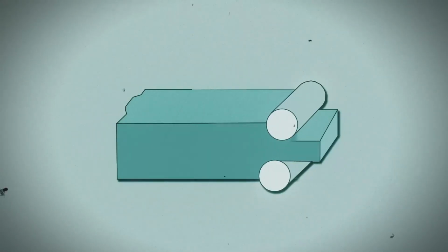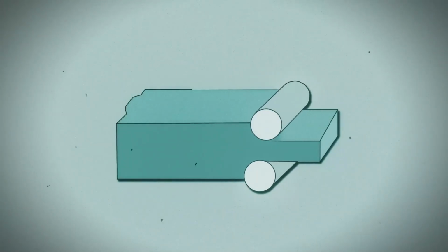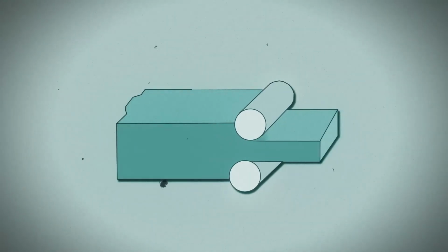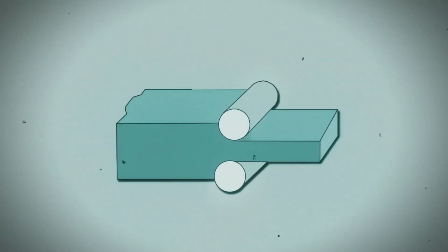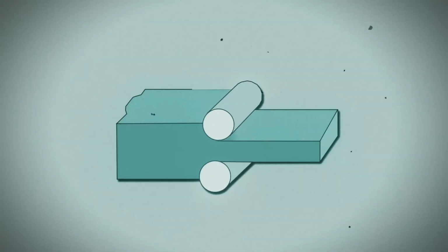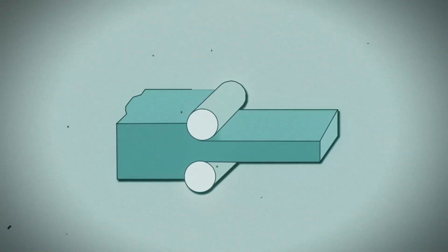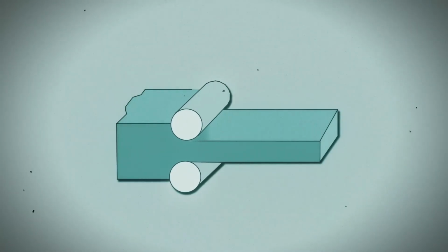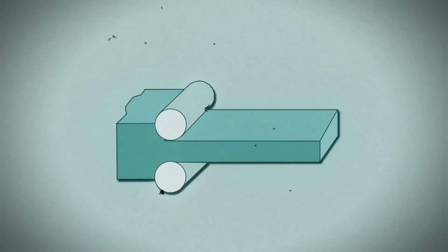The easiest to obtain is homogeneous armor produced by casting, hardened through the entire depth to increase hardness. Low strength, cast homogeneous armor has insufficient cohesion, with weak bonding between metal grains. Rolled homogeneous armor is obtained by rolling heated cast armor. Grains are compressed and stretched. The structure becomes fibrous. It is much stronger and harder to penetrate. Cutting across the grain is harder. The simplest example is a piece of wood. It is easier to cut along the grain than across it.